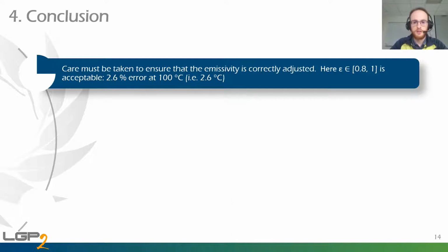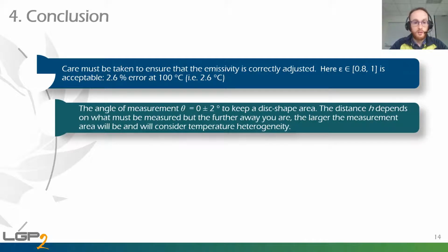So to conclude this presentation, I will say that care must be taken to ensure the emissivity is correctly adjusted. Here, when the emissivity is between 0.8 and 1, it's acceptable. We have a 2.6 error at 100 Celsius degrees. Concerning the angle of measurement, theta, it must be set equal to 0, more or less 2 degrees, to keep a disc-shaped area. The distance h depends on what must be measured, but the further away you are, the larger the measurement area will be, and will consider temperature heterogeneity.